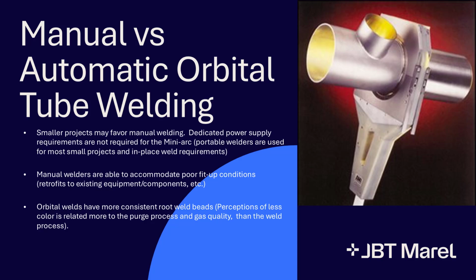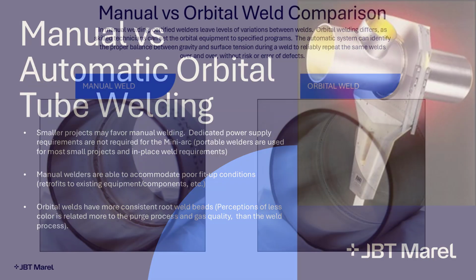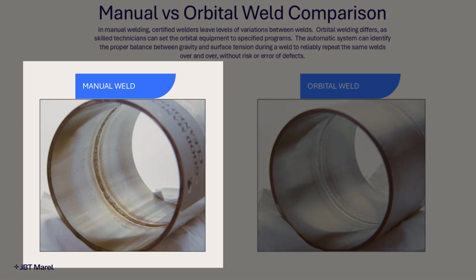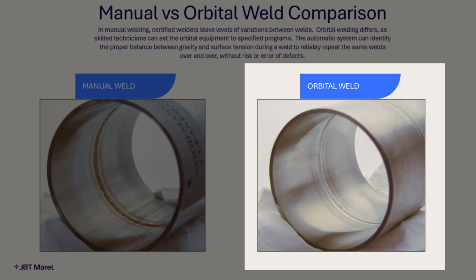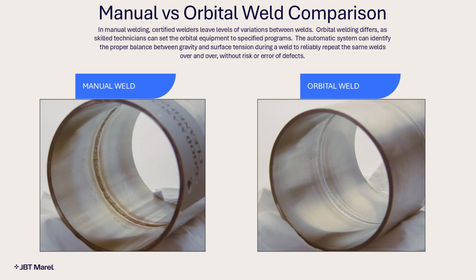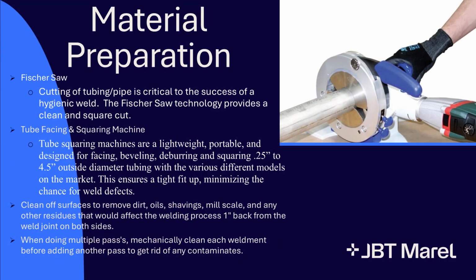With the orbital system, your welds have a more consistent root bead with minimal color. This is because the purge process is about perfect in containing the argon flow and dispersing it without oxygen being included. Up here, you can see on the left, you'll notice the color variations are much more pronounced in the manual TIG weld, along with the inconsistent bead pattern. On the right, you can see an orbital weld that got optimal gas coverage and consistent weld edges on the inside and the outside of the weld. This is because the automatic system can identify the proper balance between gravity and surface tension during a weld, leaving it virtually flawless. Next, we'll go into material preparation.